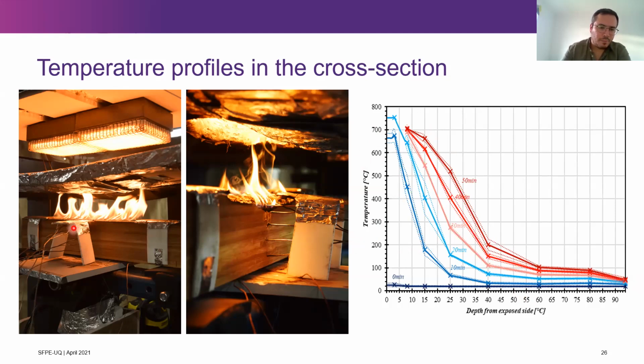Again, we set up different thermocouples. We measured the temperature profiles for different times. You have temperature against time. Before starting the test, you have pretty much the whole beam at ambient temperature. After 10 minutes, you start seeing some charring, and obviously you have higher temperatures closer to the exposed surface, and temperatures start increasing in the whole cross section after a certain period of time.